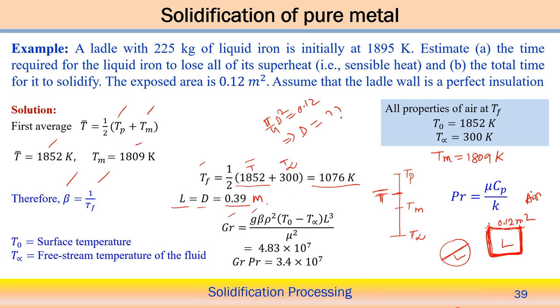So the Grashof number is calculated. The value of g we know, beta we calculate, and density is given for this fluid medium, density also known, T0 here is 1852 Kelvin. So we can consider T0 as 1852 Kelvin. In this case, all properties of air at TF, and here we can estimate T0, the surface temperature, and then T infinity. So here the surface temperature we consider is the actual average value 1852 Kelvin, T infinity 300 Kelvin, and the characteristic length and the viscosity. From there we get the value of the Grashof number, and we can further calculate Grashof number into Prandtl number, because Prandtl number equals mu Cp by K. From the properties we can find the Prandtl number, mu Cp by K. So once we get it, we can get the Grashof number into Prandtl number equal to this value. For example, this is the value.